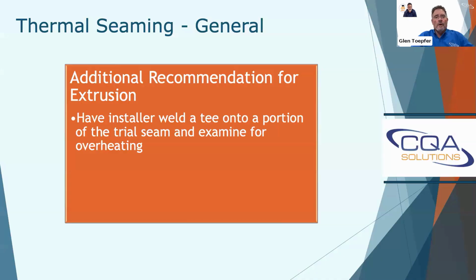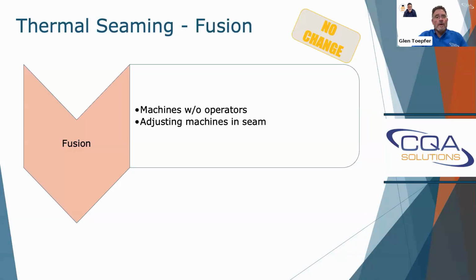Thermal seaming, additional recommendation for extrusion. What we like to see on our extrusion welds is that we like to have the welder do a T on the trial weld. You can't test that T, but you can flip it over and see if there's any heat penetration issues, and you can look at how they're joining the two together. It's a good practice, only takes a couple extra minutes.